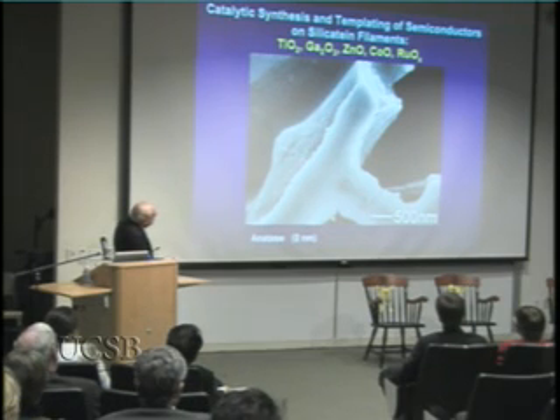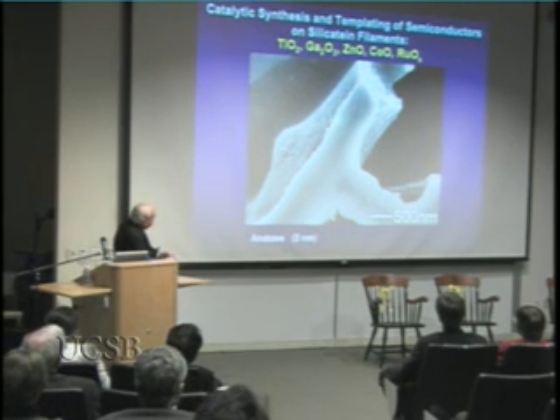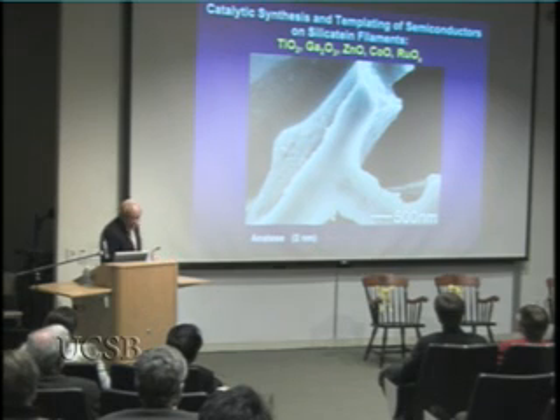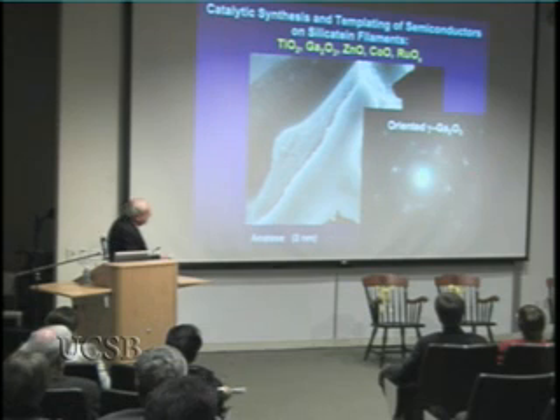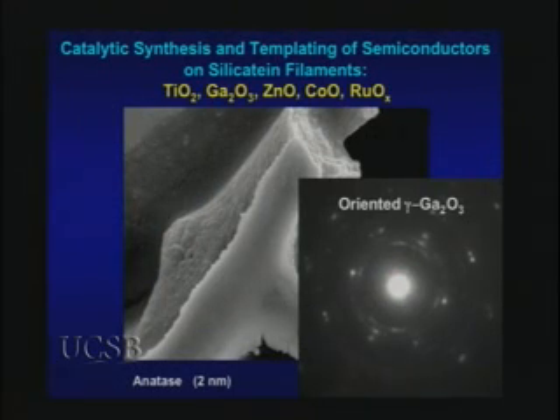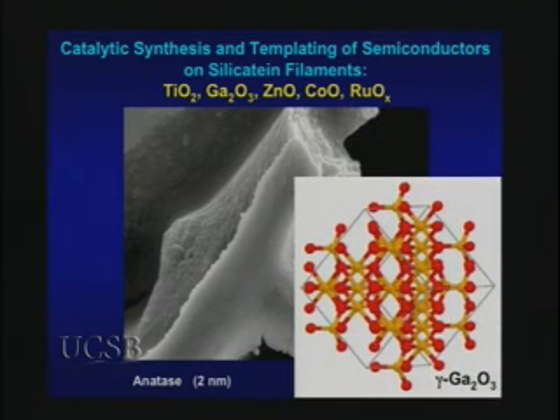Again, there's two activities that we found. The catalysis at neutral pH and low temperature. Normally these reactions require high temperature and strong acid. You can see the templating effect because the metal oxide semiconductor is deposited on the surface of the protein. And with this approach, we've been able to make a wide range of interesting semiconductors. In some cases, the metal oxide that's produced, like the gallium oxide, is highly crystalline. And in fact, the nanocrystals are deposited with an orientation along the fiber axis of the protein, suggesting that there really is an atomic level of coordination between templating, truly, between the protein surface and the growing semiconductor. In this case, we found that the gallium oxide that's made is a form that's normally made only at very high temperatures. Here, the protein's able to stabilize the growth of this form at 16 degrees centigrade, quite chilly.